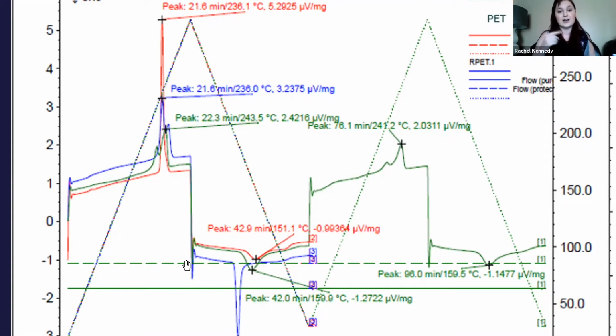Like I said earlier, this green one is a little bit longer because it was done twice. The reason we did it twice is because this was a cradle to grave to cradle material that we wanted to be able to reuse after its life cycle had ended. So this second peak here on the other side is the melting temperature of your overall combined material. So this is the mixture of your sheath and your core. So this is a slightly different temperature.